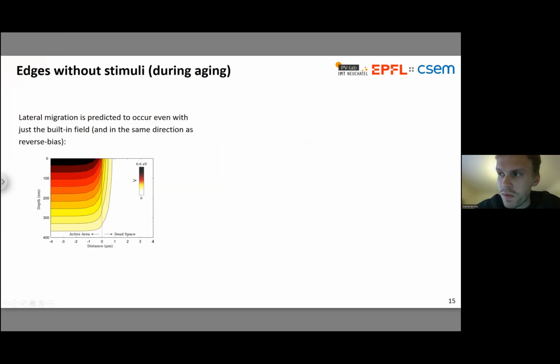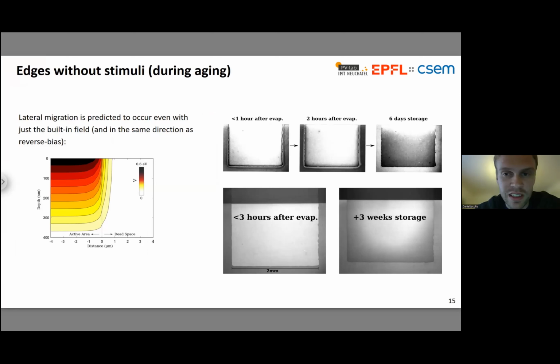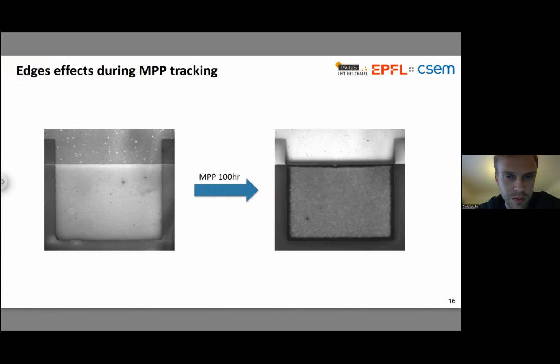And in terms of other predictions of this hypothesis, I mentioned a few slides ago that just the built-in field is enough to already drive migration. So the question is whether we actually see things happening in the absence of applying any bias. And the answer seems to be yes. You have to look a little bit closely. The images that I'm showing in these figures are contrast adjusted. But very typically, I see when I look at devices that have been in storage, before I've done anything to them, before I've so much as measured them in our solar simulator, I start to see the development of these patterns. And it starts occurring as soon as I evaporate the top electrode. So that's when the clock starts. And then you see these patterns of migration happening progressively over time, even when they're just kept in darkness inside the glove box, so in gas storage. So indeed, it seems like the built-in field is enough.